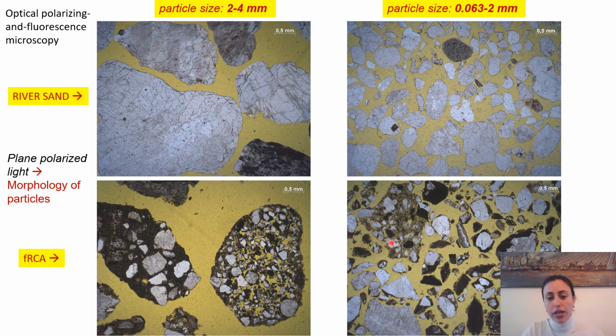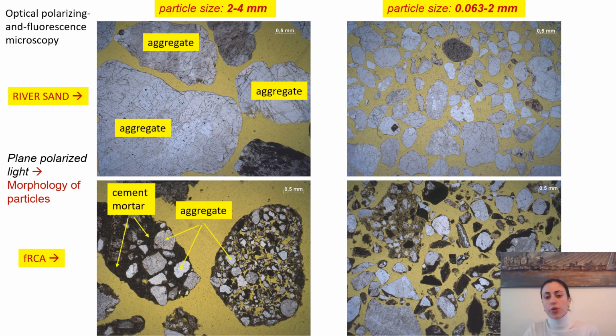On the other picture, on the right, for the smaller particle size, you can see that there are particles where a lot of cement paste is, and particles which consist only of quartz, or let's say just mineral particles. So now you can see the main difference here is the cement paste compared to the river sand. And of course, this material is mainly crushed, so the shape is also very important.